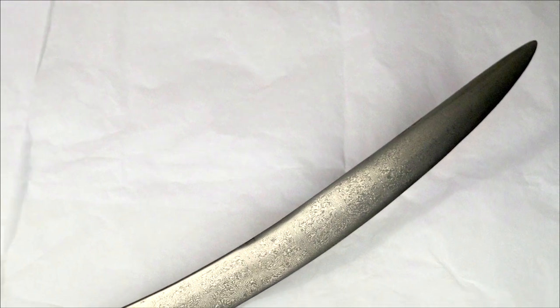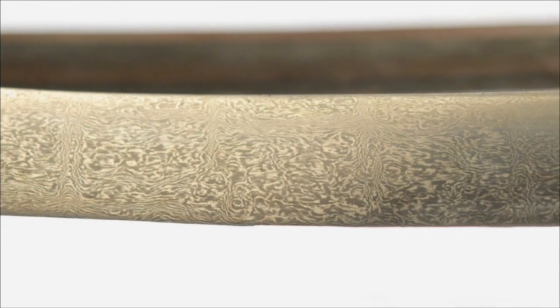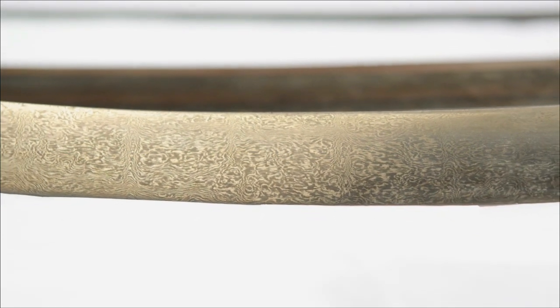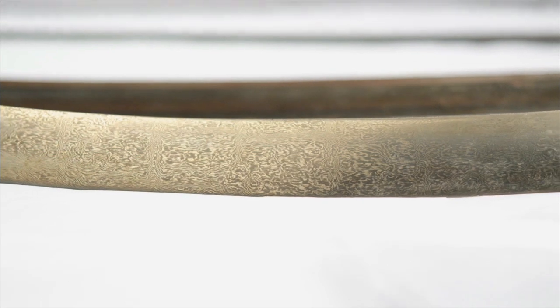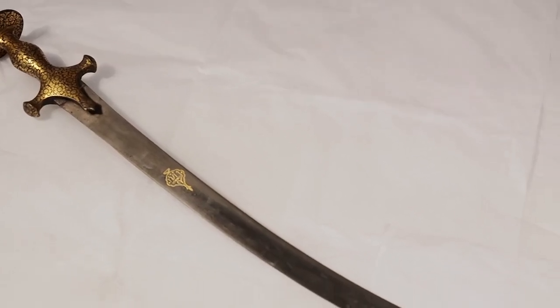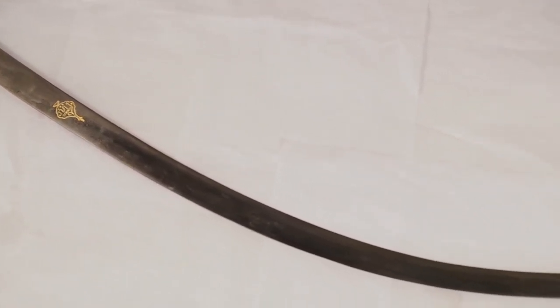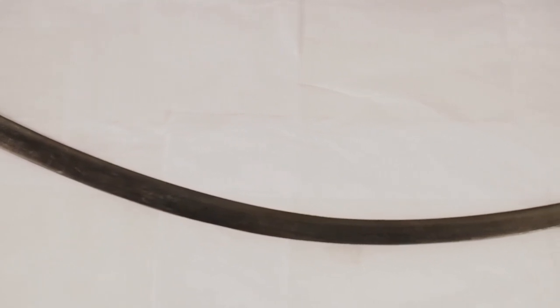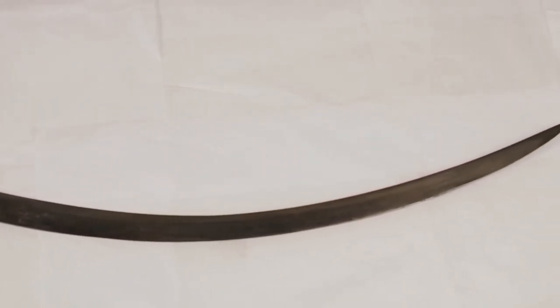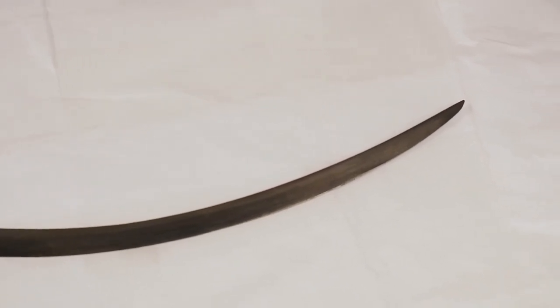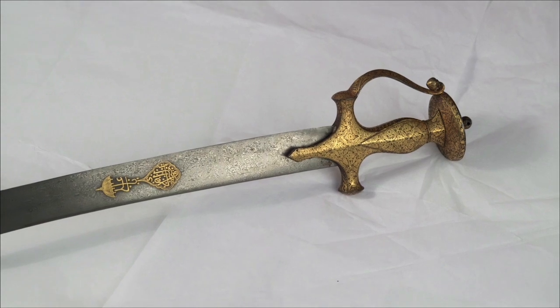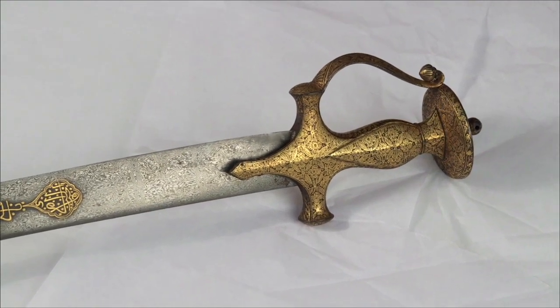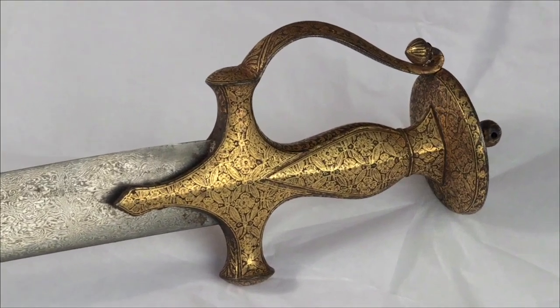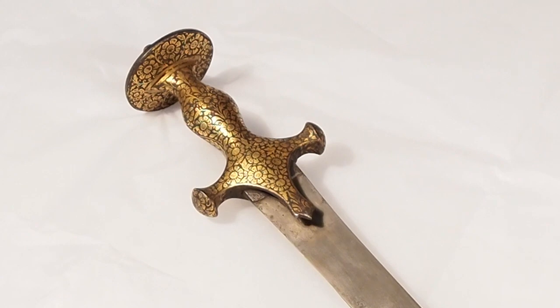This is the sword which belonged to the early Mughal period, which we can say was made during the period of Akbar. And here you can see the watermarks, very clearly, on the blade, which show the excellent quality of the wootz steel. And the curvature in the blade was a feature of the Mughal swords, and it is a single edge blade, not a double-sided edge blade. And here you can see the hilt of this sword, it is beautifully decorated. You can see that these floral and creeper motifs are in gold.